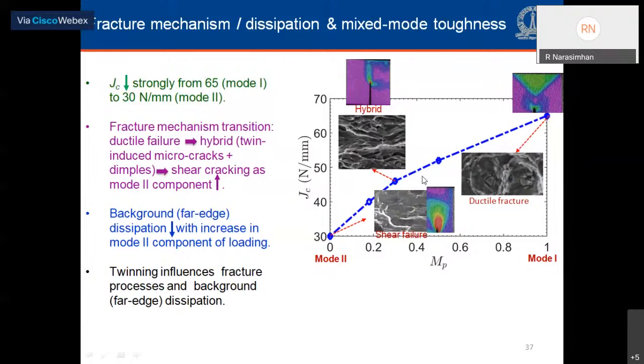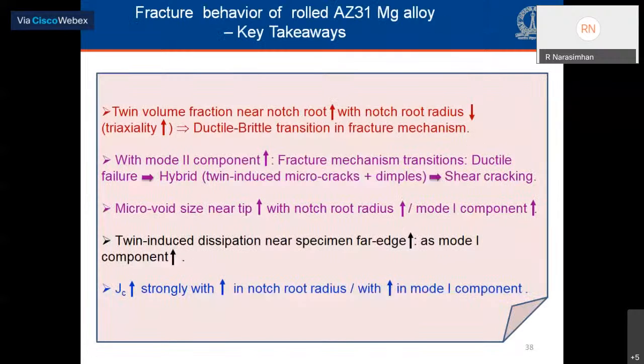And as you transition towards the mode 2 case, in the mixed mode case, there is a transition to a hybrid mechanism with more brittle features, twin-induced brittle features seen on the fracture surface, as well as less dissipation caused by twinning in the background plastic zone. And as you go further down towards the mode 2 case, far less twinning-induced dissipation and shear mode of failure. So the combination of these two factors, the transition in the fracture mechanism, as well as less dissipation caused by twinning, is possibly the reason for the large change in the toughness as you go from mode 1 to mixed mode.